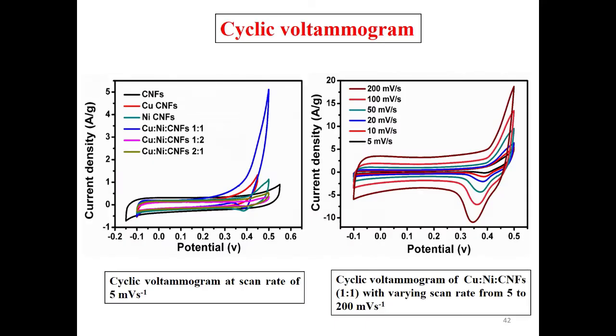We have prepared some materials: copper nickel nanofiber of different ratios, 1:1, 1:2, 2:1. Copper carbon nanofiber and nickel carbon nanofiber are also used for the cyclic voltammetric study. Copper nickel carbon nanofibers show high potential with respect to current density. Cyclic voltammetry at a scan rate of 5 millivolt per second shows that the reverse reaction is very effectively formed.